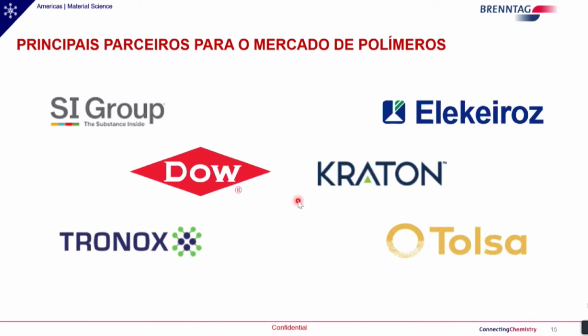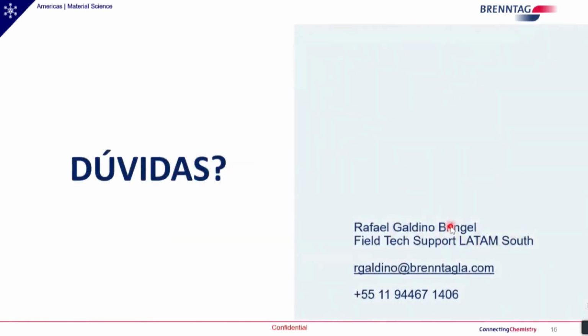We are working quite strongly with the circular line, and this afternoon I'm going to speak more about this. Tronox is titanium dioxide for white coloring, and the Tolsa line, which is a synergy agent for flame retardants. Quite an interesting material that plays the role of suppressing smoke, reducing the dosage of anti-flame agents, and it also increases the mechanical properties of the material because in itself it is a reinforcing agent. So it's a very special and interesting material that we offer in this market.